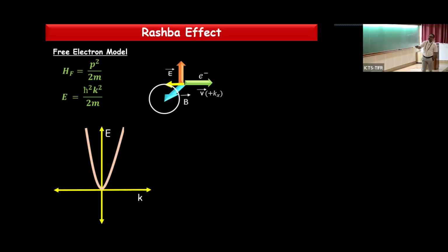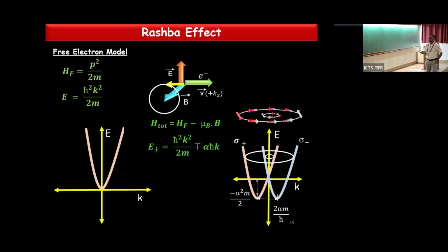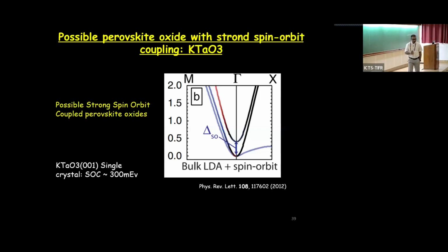Now if you invert the direction of your motion, the direction of this quantization changes, and this gives rise to spin-momentum locking, known as the Rashba effect. Now your energy is no longer k squared like; it has a k squared plus or minus k dependence, and your one parabola is split into two parabolas. Instead of one Fermi circle, you have two Fermi circles with spins rotating opposite to each other, giving rise to the idea of spin chirality in the system. A possible perovskite oxide which can have a very strong spin-orbit coupling is potassium tantalate.